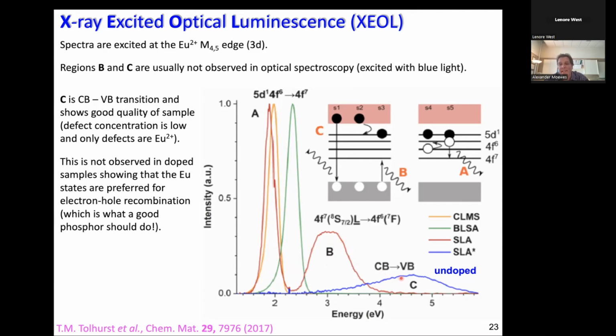But what you see is, as soon as you dope it and you go from the same sample, SLA, from the blue spectrum, undoped, to red, doped, then this basically becomes dead flat, and all the energy, or all the decays, are channeled toward the channel that you want, the visible emission channel 5d to 4f. So this was quite instructive to see in this way.